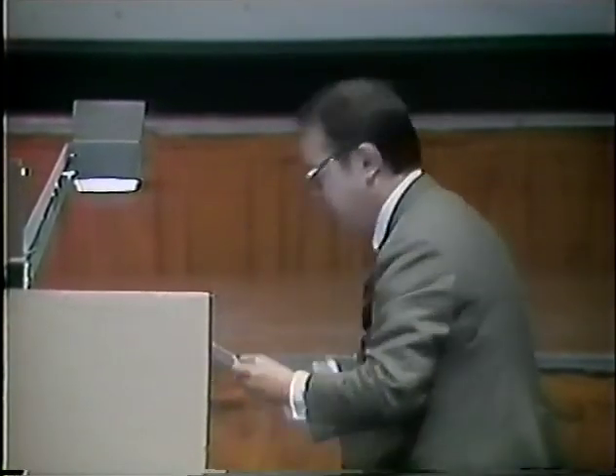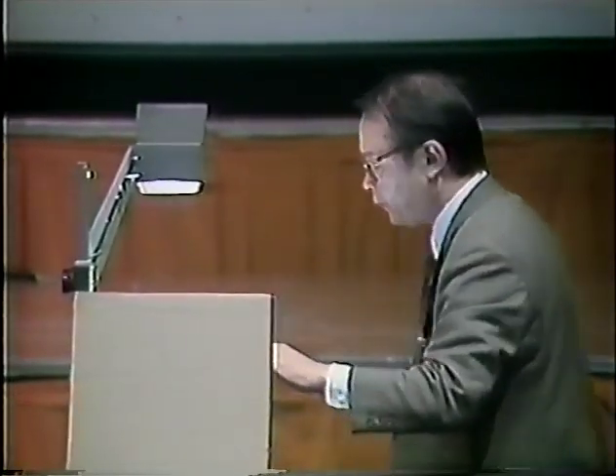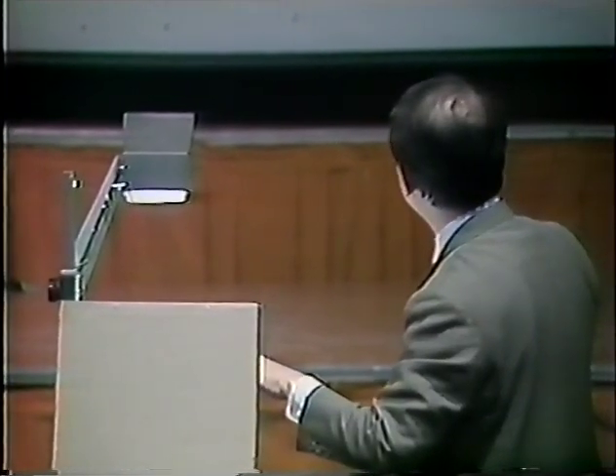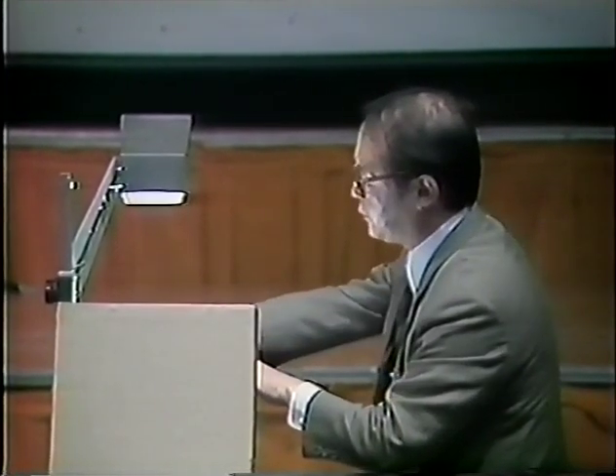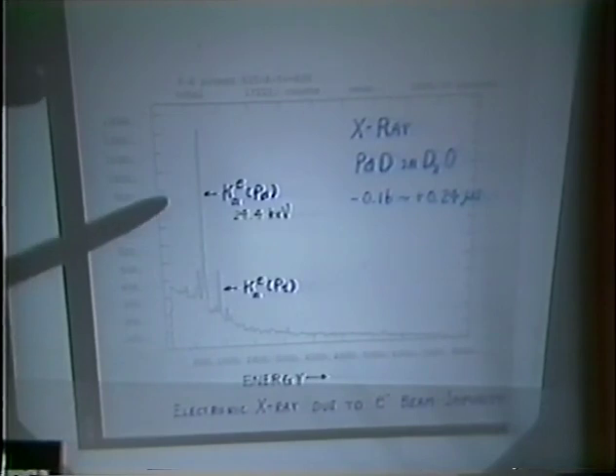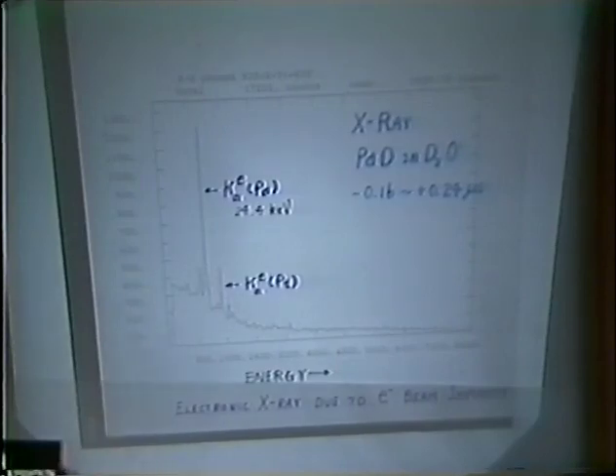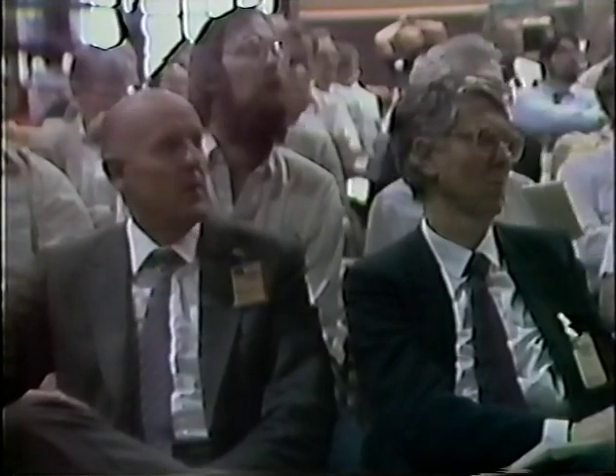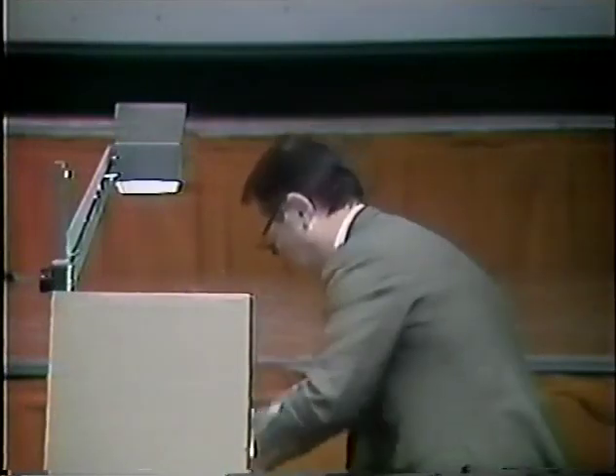The X-ray yield, this is again the X-ray yield at the time of the muon beam arrival. Because of the small impurity of the muon beam, we have X-ray peaks from the palladium and platinum. But when we make a delay after 240 nanoseconds, there is no significant peak at all, demonstrating no significant charged particle emission from our system.